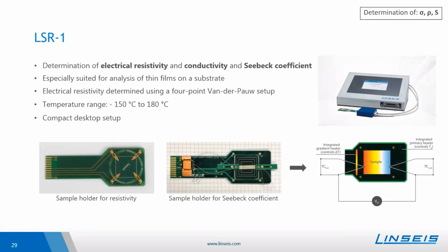There's also the so-called LSR1, which stands for Linseis Seebeck and resistivity meter. It is a very compact desktop setup and looks like that. It can also determine the electrical resistivity, conductivity, and also the Seebeck coefficient. And the setup is especially suited for the analysis of thin films on a substrate. The electrical resistivity is determined using a 4-point Van der Pauw setup.